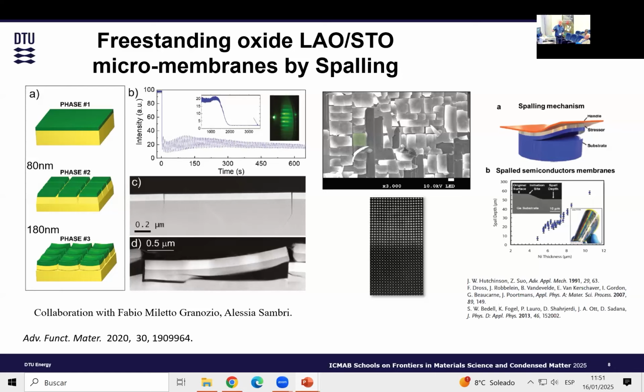So this is how it flakes. At the beginning, it's growing layer by layer. We know it, and after about 80 nanometers, you get cracks which are perpendicular to the surface. And after approximately 180 nanometers, we get cracks which are parallel to the surface, and then a membrane detaches. Interestingly, those membranes detach along the crystallographic direction of the crystal, so you get a well-defined crystal out of them. When we make a cross-section of this crystal, we see that they are intact.